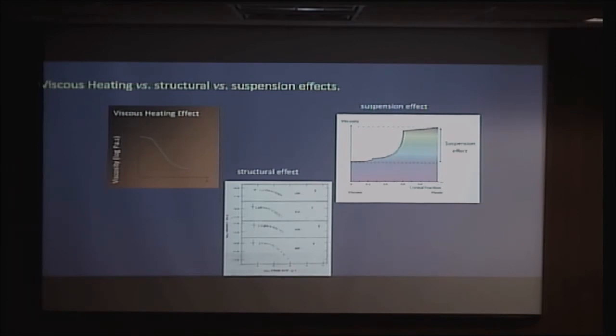Congratulations to us. It's going to be complicated, right? So we know that there's viscous heating. We can quantify it. It's fairly straightforward. The equations are fairly straightforward. They scale to the strain rate squared. We know that there are great suspension effects in these liquids, so understanding their rheology also requires understanding their crystal content, their bubble content, the chemical effects of producing the crystals and bubbles, which is differentiation in a magmatic sense, and the physical effects of the presence of the crystals and bubbles, which is the physical rheology of the system.